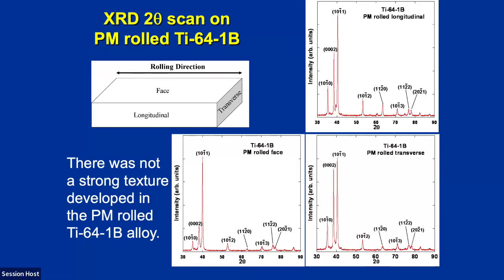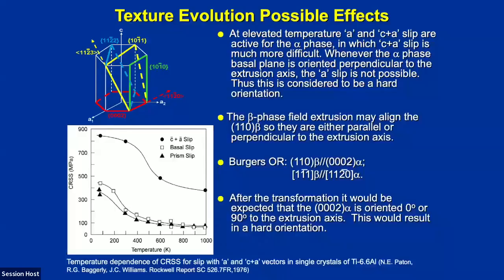We look at this with increased temperature, the critical resolved shear stress decreases for all the slip systems. It decreases significantly even for the C plus A slip. And when the alpha basal plane is oriented perpendicular to the extrusion axis, A slip is not possible. Therefore, we could have a reduction in the elongation to failure. And so after the transformation, it would be expected that the 002 basal plane is oriented 0 or 90 degrees to the extrusion direction. And this would result in what we call a hard orientation, something that would be high strength, but may not be the best in terms of ductility.